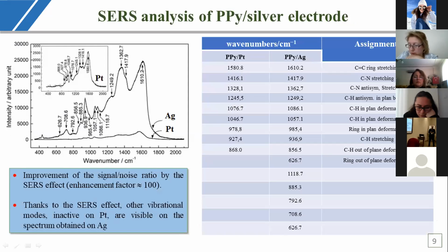The ex situ Raman spectra of polypyrrole film covering platinum and roughened silver electrode are presented in this figure. As shown, the spectrum recorded in the case of silver is more intense with better resolved peaks. The SERS enhancement factor was evaluated at 100 in this case. Moreover, thanks to the SERS effect, other vibrational modes inactive on platinum are visible on the spectrum obtained on silver.